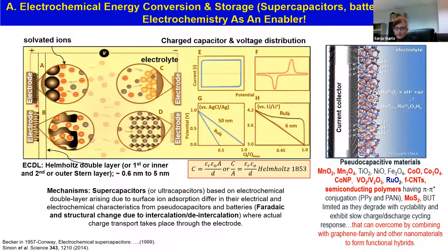You have studied electrostatics in your undergraduate physics: if you have two parallel metal plates, a parallel plate capacitor, separated by a certain distance and having a certain area, its capacity is directly proportional to the area and inversely proportional to the distance between the two plates. If you decrease the distance, here we are talking about 1 to 5 or even less than 1 nanometer. The typical carbon capacitors that you can buy from shops are around 5 millimeter. So if we reduce the distance by six orders of magnitude, keeping everything else the same, you increase the capacity automatically by six orders of magnitude. And this is the fundamental play for energy storage in supercapacitors or ultracapacitors.